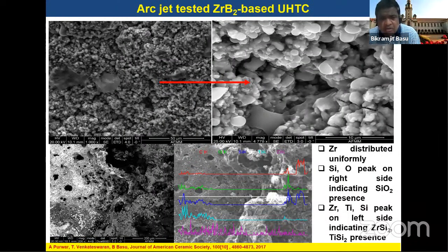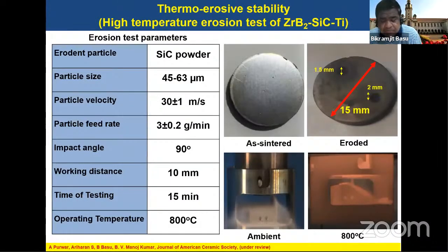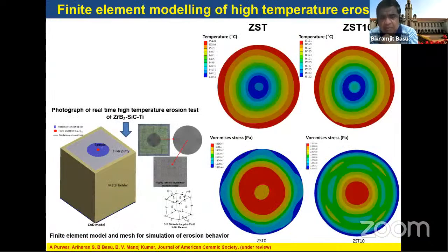And this is how this arc jet tested sample, that exposed sample, appears after testing for 30 seconds. Now, the second performance qualifying test that we have done is a high temperature erosion test. In view of the limitation of the experimental setup, we could not do it at a temperature above 1000 degrees Celsius, but we have done it at a temperature of 800 degrees Celsius on the 15 millimeter diameter sample. And as I said before, we always combine computation and experiments together.